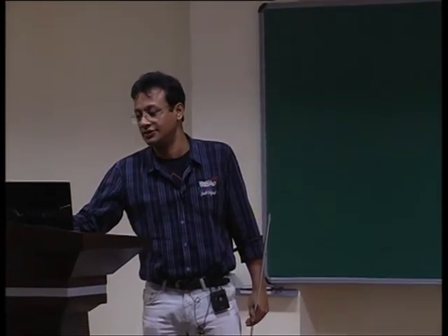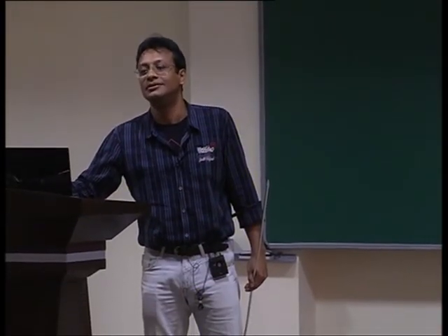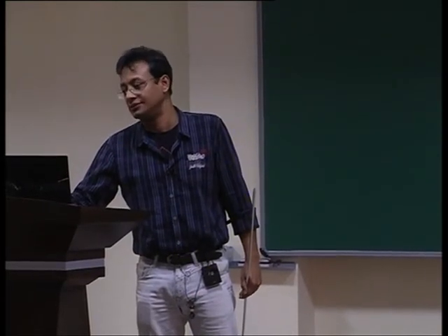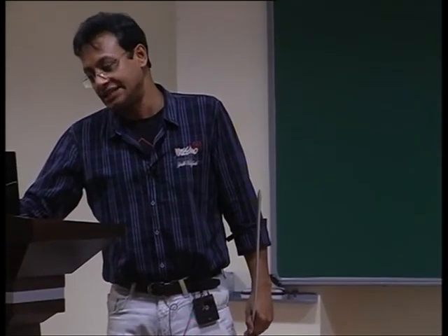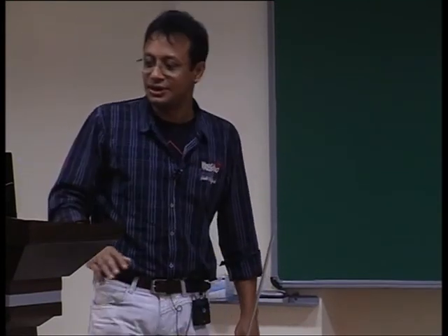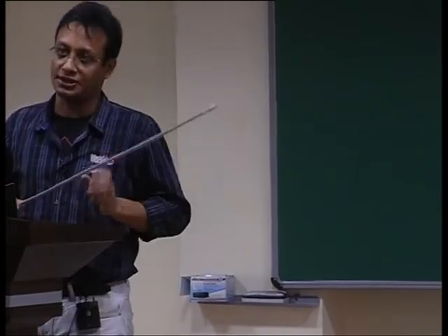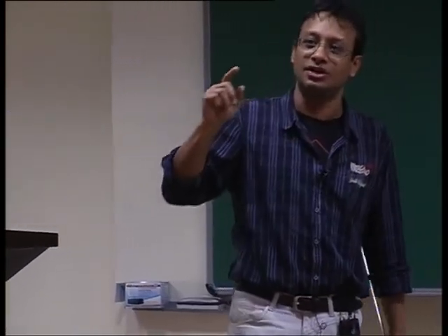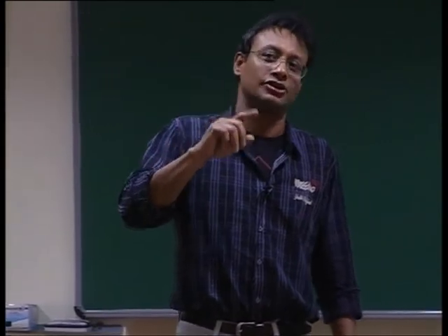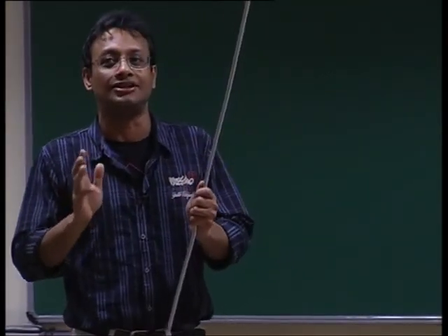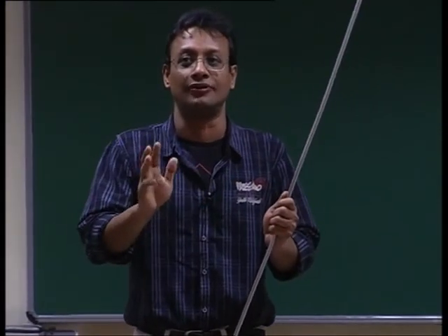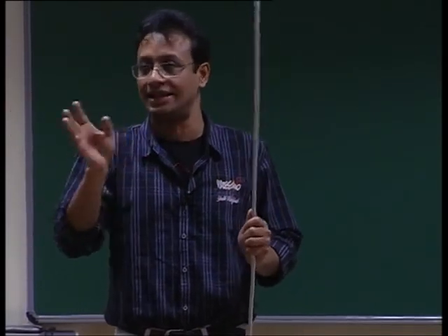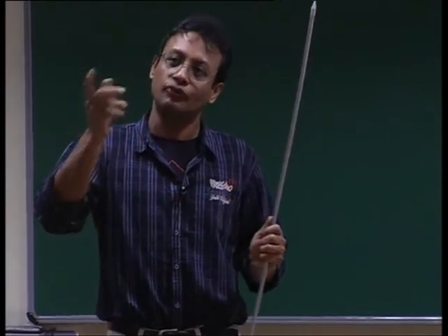No, before that, there is this data, this one. For the green curve, there seems to be some asymmetry towards the high end of the magnetic fields. You're right. There are two possibilities to my understanding. Most mesoscopic samples, because of the irregular shape, the magnetic resistance can actually become asymmetric between positive and negative magnetic field. Sometimes asymmetry is attributed to the existence of local moments, but that is not the case here.